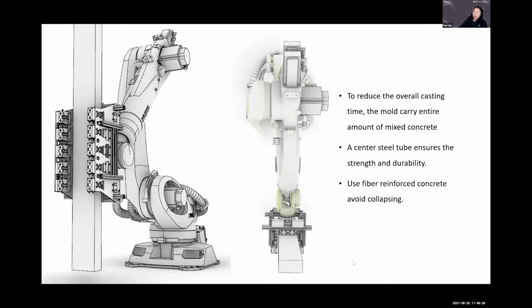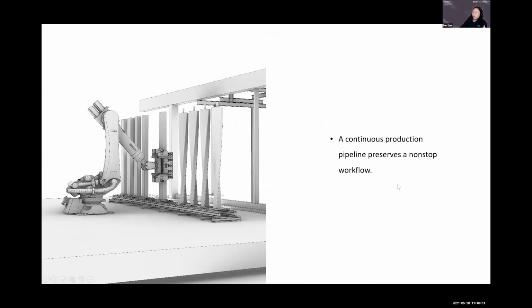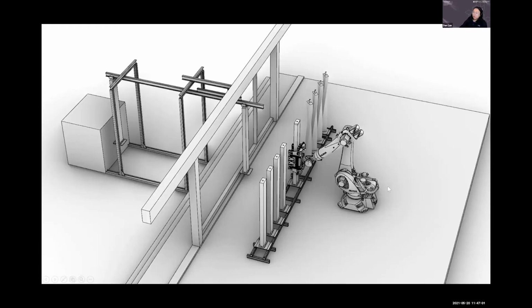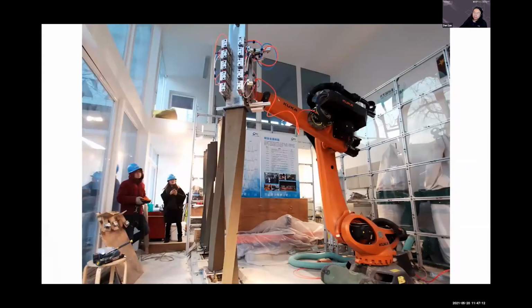So different from the original process of highly customized concrete being poured during the extrusion process, we had an alternative process where we were using a uniform stainless steel mold and have the bulk concrete cured altogether, and it deforms the concrete while being extruded from the mold and being rotated. The benefit of this process is that we can significantly reduce the curing time of the concrete. Basically they're pre-cured to the right moment, and they can be extruded in this more pipeline method.